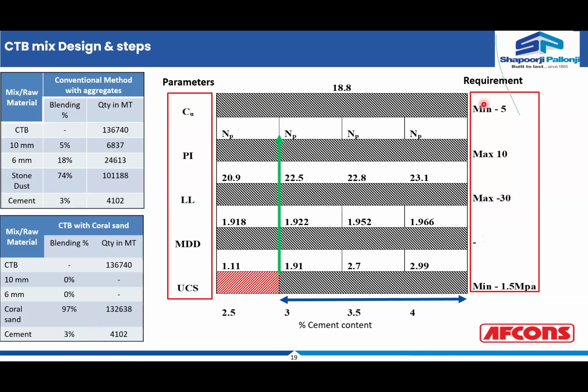So if you see the graphical representation, the parameters like CU, plasticity index, liquid limit, MDD, and UCS. UCS is ranging between 2.5 to more than 4. And with the increase in the cement content, say 2.5, 3, 3.5, 4, and above, you can see that my basic minimum UCS is achieved with 3% of the cement dose. And of course, the maximum dry density is well in the range of what is being achieved using the normal conventional mix designs. There is not much variation in other parameters.